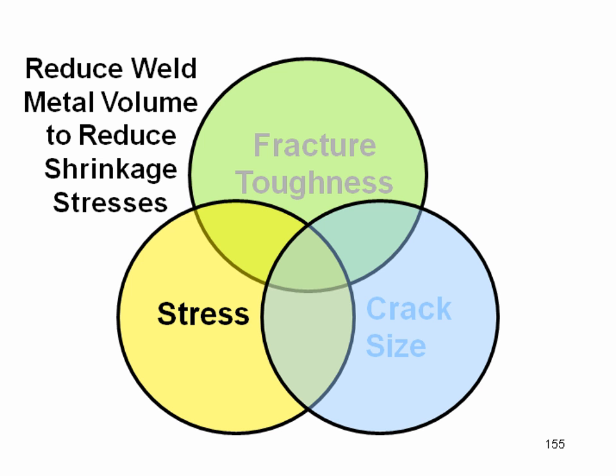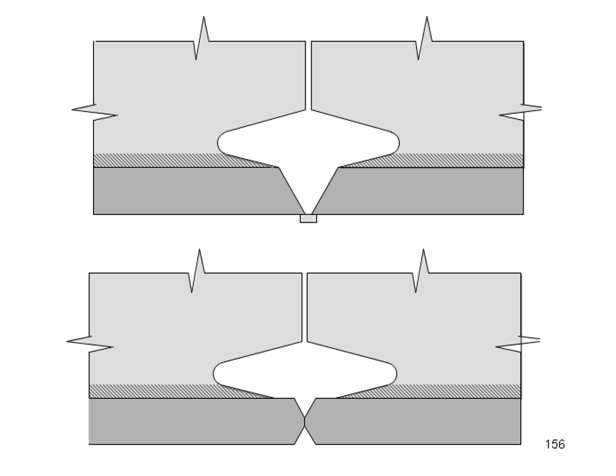And one of the things we need to do is recall that these are residual stresses from welding, and if I can reduce the volume of weld metal, I can help reduce the shrinkage stresses. So this is where we look into the detailing. Is a single V-groove weld or should a double V-groove weld be used? Well, the double V typically has less weld metal involved in the joint. That's going to be helpful to us.